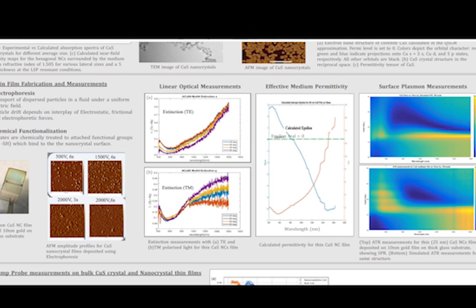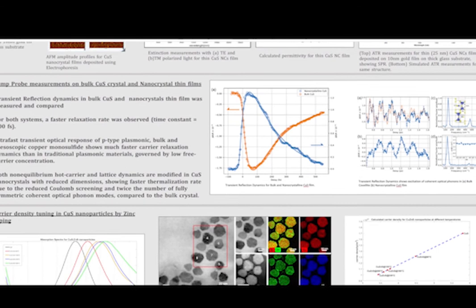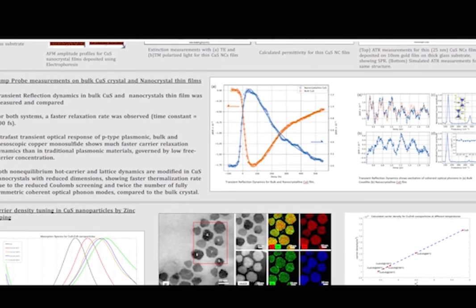Interestingly, the extracted optical permittivity of the effective medium of these thin films predictably had a plasmonic character to it, and we subsequently demonstrate the presence of surface plasmons on these nanocrystal films. We further show interesting physics of thermalization of hot carriers in copper sulfide bulk and nanocrystals using pump and probe transient measurements. The result shows that thermalization happens faster in copper sulfide compared to conventional metals owing to the lower carrier density in copper sulfide. We also detect coherent optical phonons in the bulk CuS crystals as well as in the nanocrystal films.